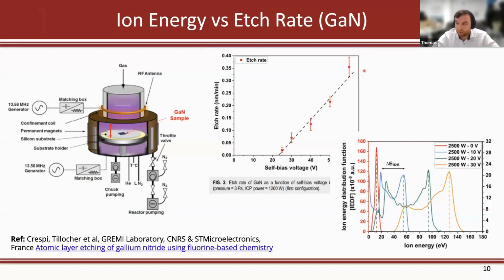Now, during this experiment, there was a simultaneous measure of the ion energy distribution function with one of our Semion sensors. You can see here, the distribution function is really quite broad. In this case, with the yellow curve, you have ions at 60 and 80 and 100 and 120 and 140, even some up at 150, right? So you have a really, really broad spectrum.